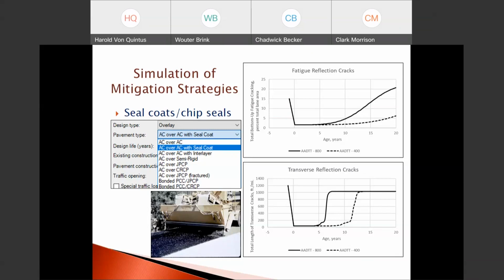So doing that, the graph on the top right is the amount of bottom-up fatigue reflection cracks. The graph on the bottom is transverse reflection cracks. On the graph on the top, the short dashed line is for lower traffic, trucks of about 400 per day. The solid line is for double that, 800 trucks per day. And so you can see trucks do make a significant difference.